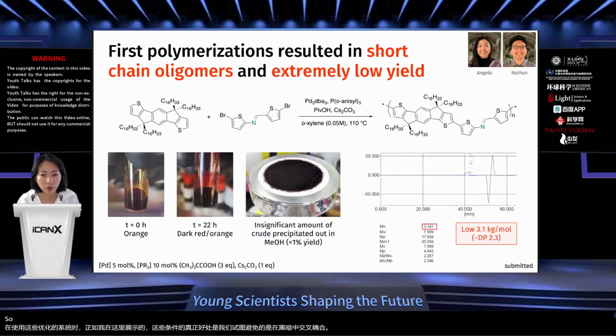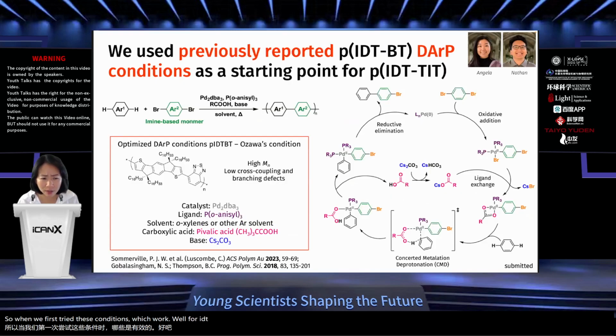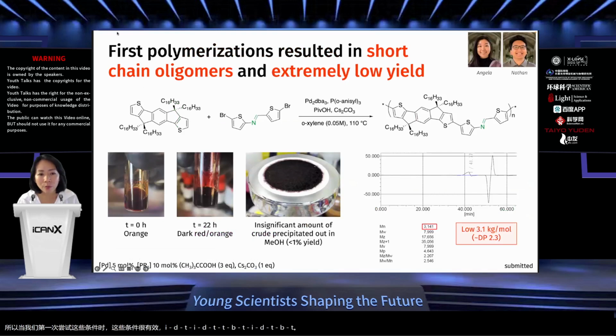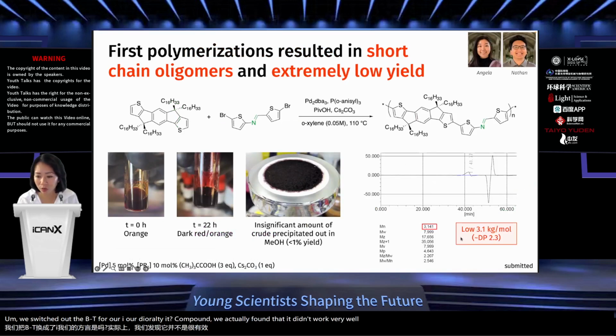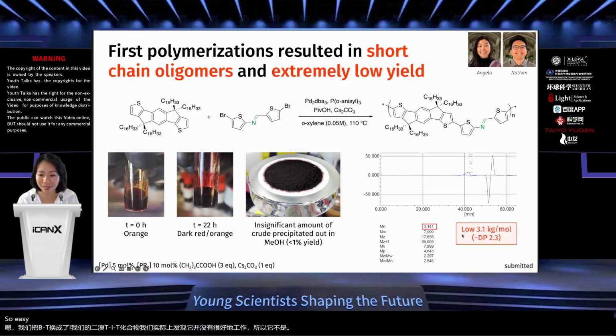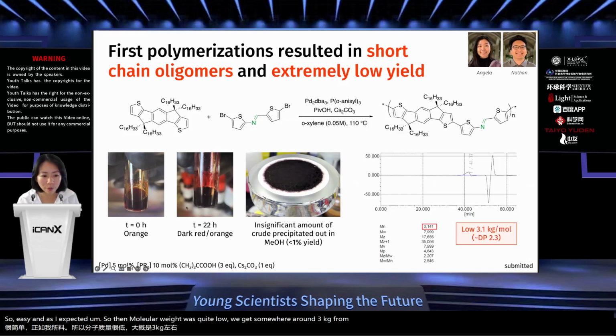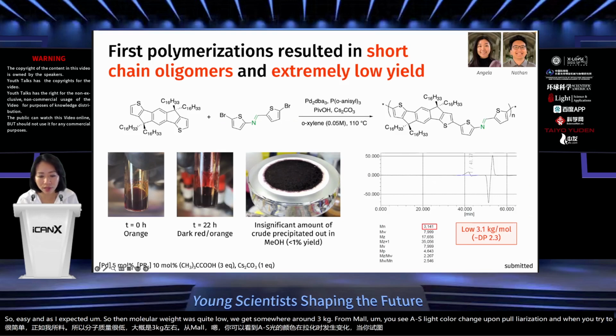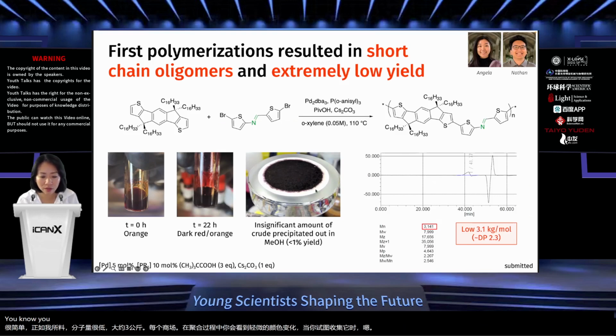So when we first tried these conditions, which worked well for IDT-BT, we switched out the BT for our dibromo TIT compound. We actually found that it didn't work very well. So it's not so easy as I expected. The molecular weight was quite low. We get somewhere around 3 kilograms per mole. You see a slight color change upon polymerization, and when you try to collect it, you get some sort of material that's really difficult to precipitate out.